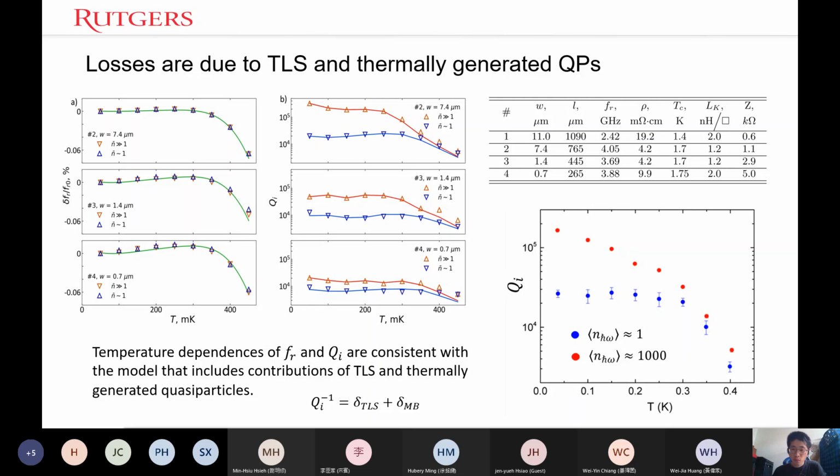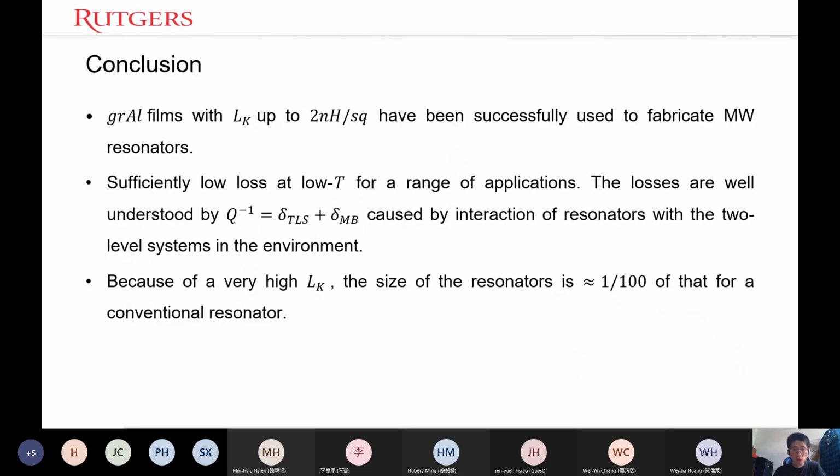All right. So we're able to fit these two curves reasonably well. As we just addressed in the previous question, the increase of this quality factor with microwave power can be explained by the saturation of two-level systems, in the regime where both two-level system energy levels have almost the same occupation probability at high microwave power, where it's about 1,000 photons.